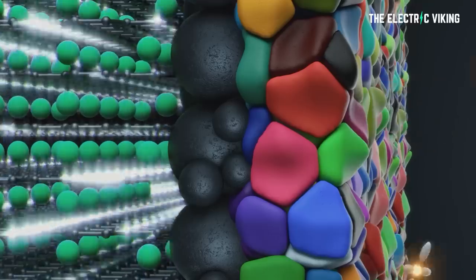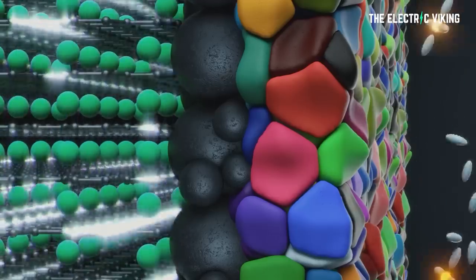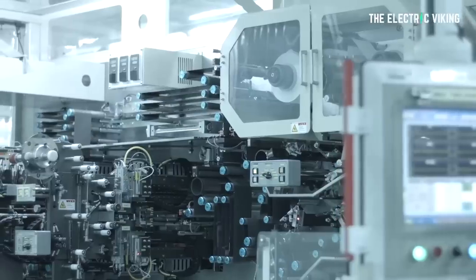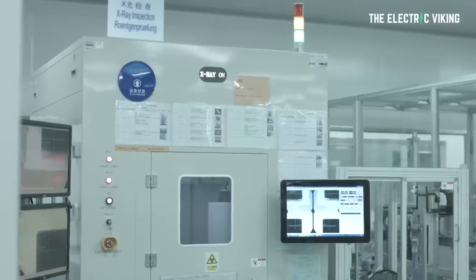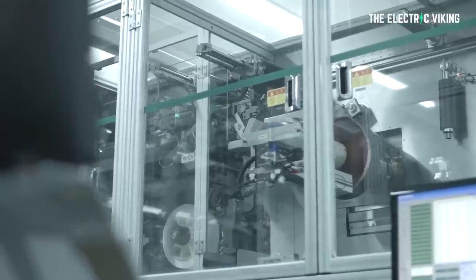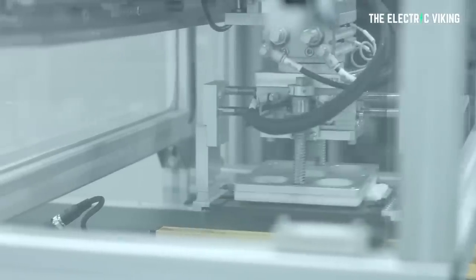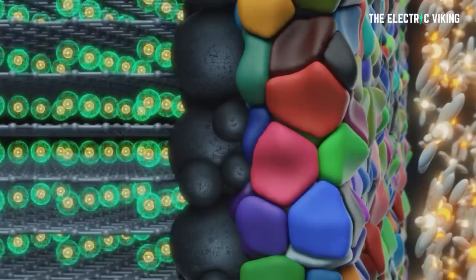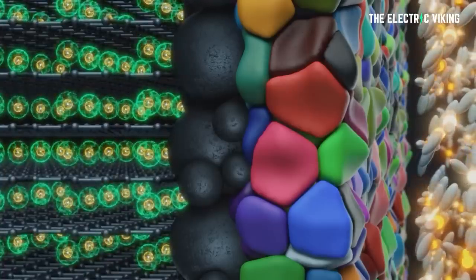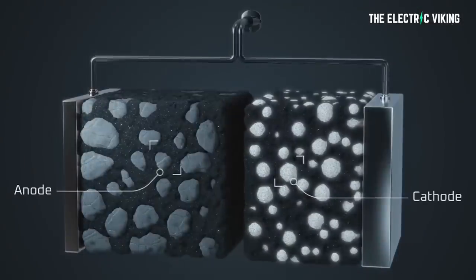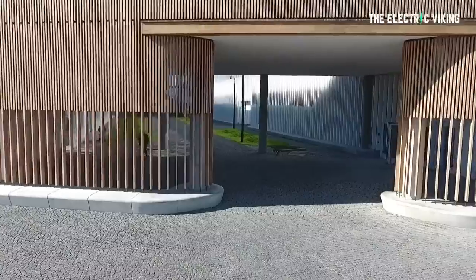In addition to denser packing, the spherical shape of the crystals reduces the area of contact with the electrolyte, minimizing unwanted interactions that, over time, cause cathode degradation, thus battery degradation and range loss, due to crack formation in the particles of conventional NMCs. This is one of the key reasons why batteries degrade. This should prolong the operating life of the cathode, and therefore the battery as a whole, leading to far less battery degradation over time in lithium ternary batteries, which is one of the big drawbacks of lithium ternary batteries versus lithium iron phosphate batteries.